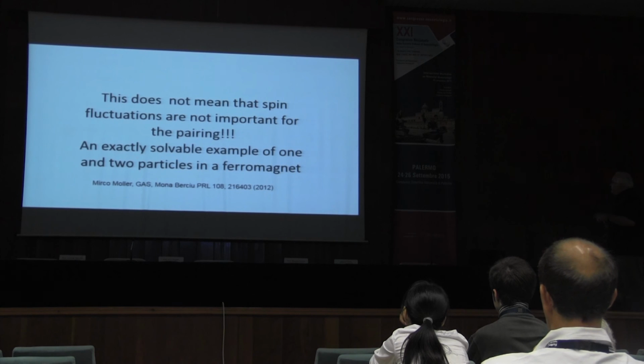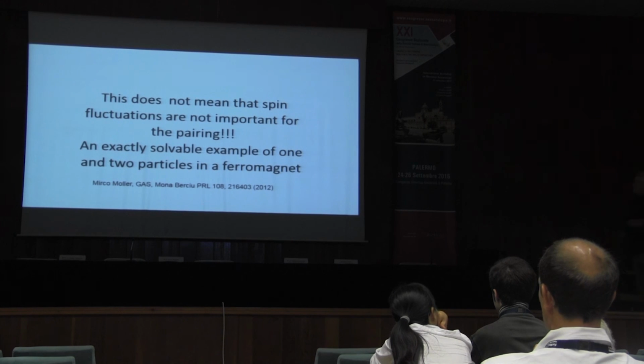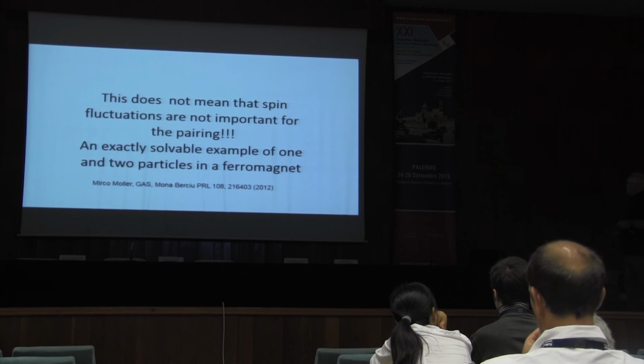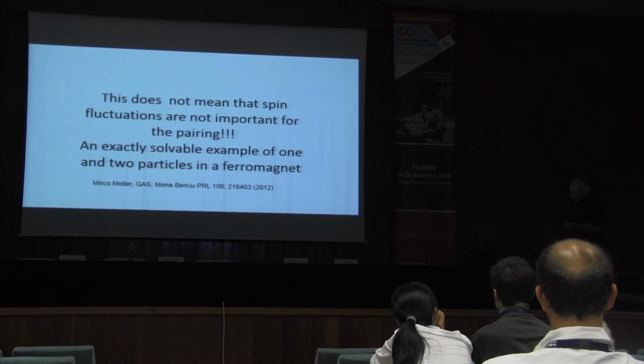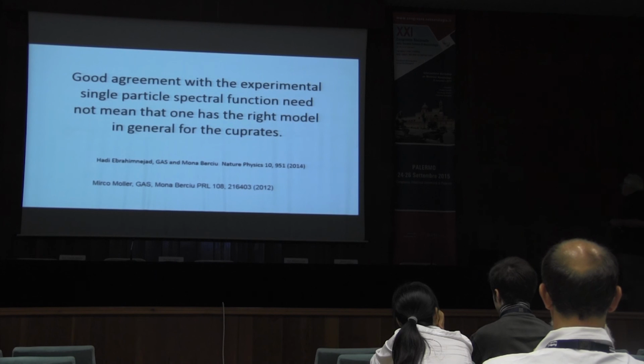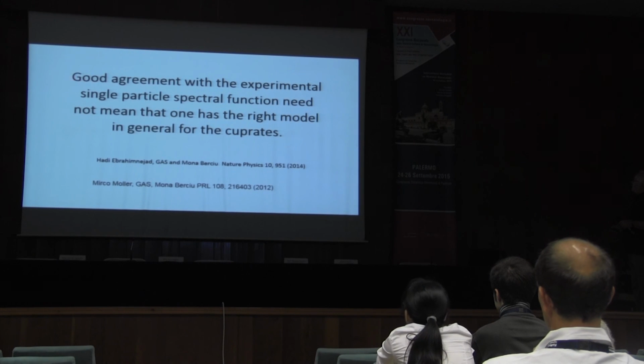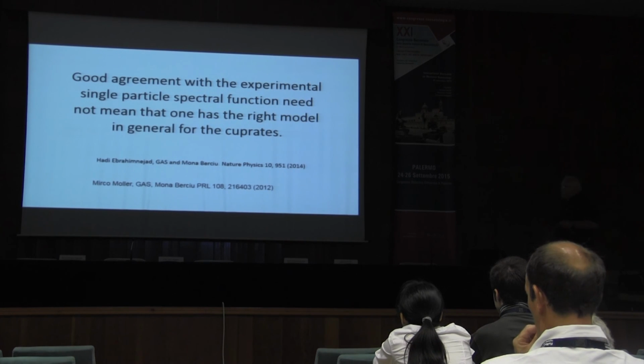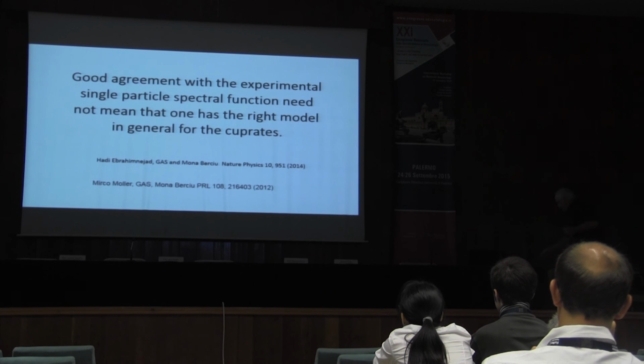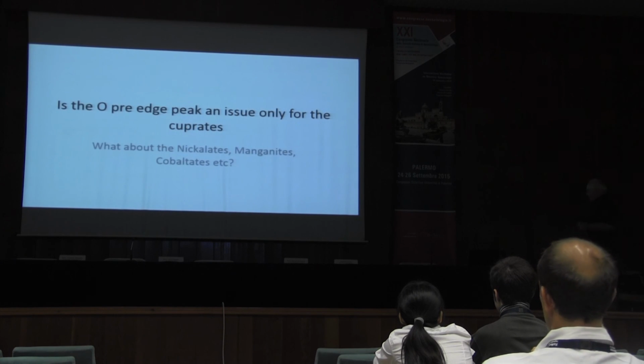This, however, does not mean that spin fluctuations are not important for the pairing, because we've also shown in an exact type of model calculation that even though you may have perfect agreement with the single particle dispersion leaving out the spin fluctuations, these still may be the thing that are the glue that give you pairing. And also another statement: good agreement with experimental single particle spectral function need not mean that one has the right model in general for the cuprates, because there you have strong pairing type interactions.